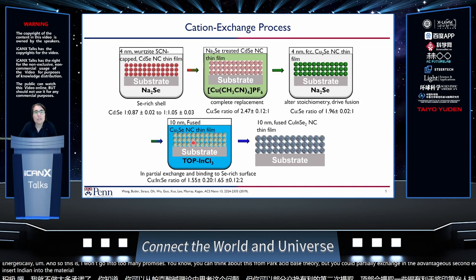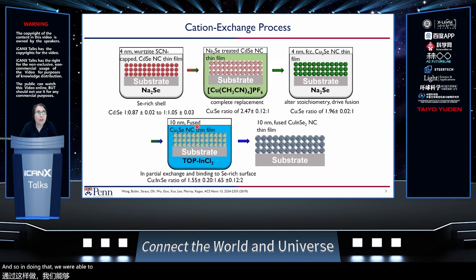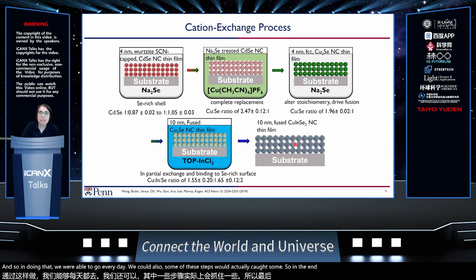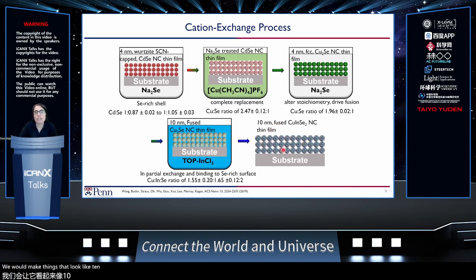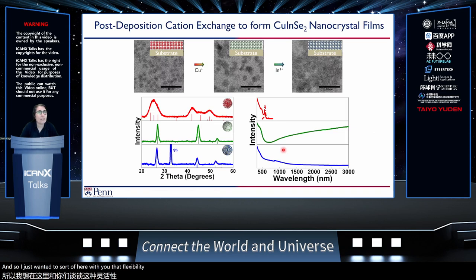And so in doing that, some of these steps would actually cause some fusion. So in the end, we would make things that look like 10 nanometer grain size copper indium diselenide. I just wanted to share with you that flexibility. You could characterize and show, as we go through these steps of cadmium to copper and then add indium to make copper indium diselenide, you could characterize that by diffraction measurements.